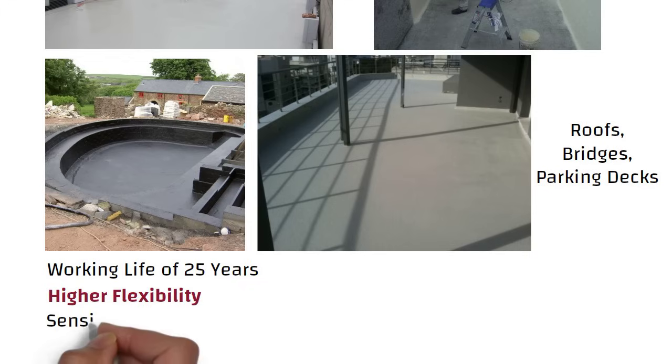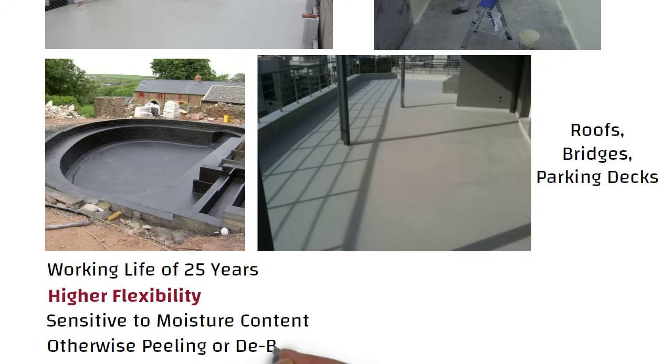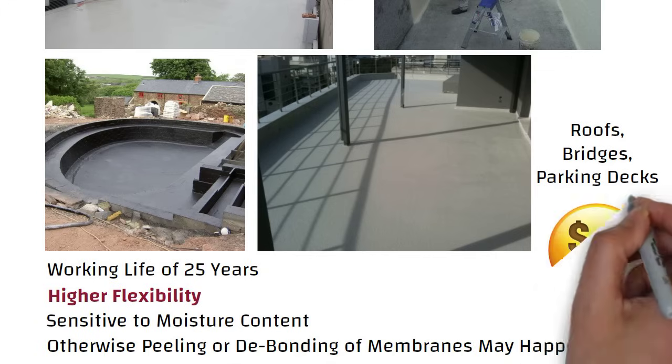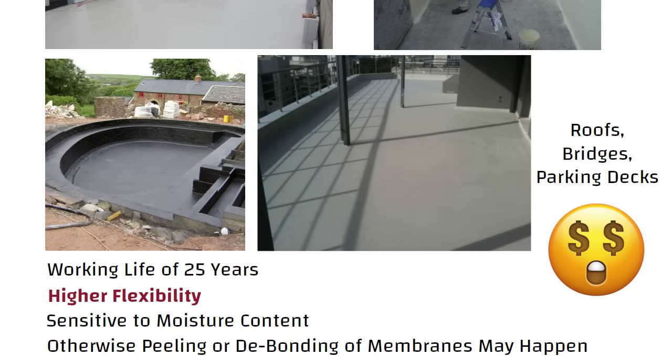Polyurethane is very sensitive to moisture content. Therefore, before application, one has to be very careful evaluating the moisture content of the concrete slab. Otherwise, peeling or debonding of membranes may happen after some time. This waterproofing method is expensive as compared to all the other methods.